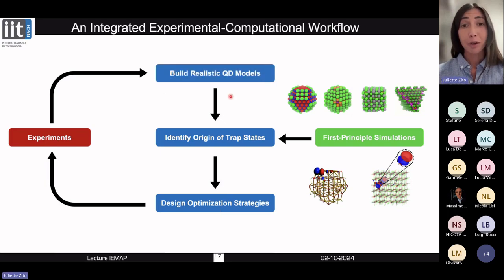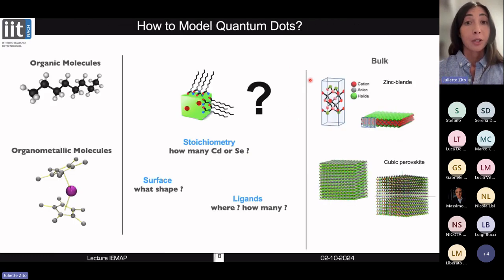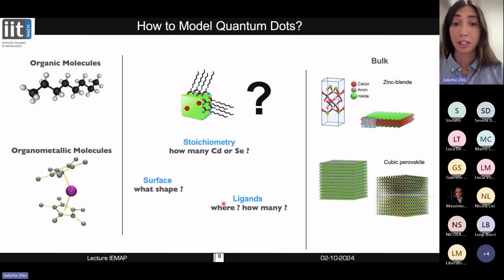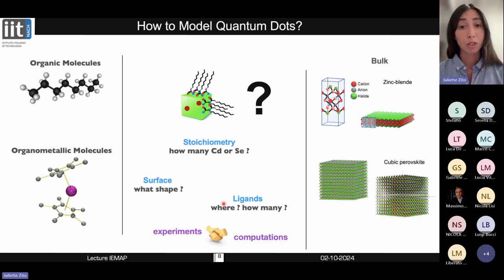So everything starts with building a realistic quantum dot model in order to understand and describe in atomistic detail the surface of your quantum dot. This is already a challenging step because, unlike organic molecules or bulk materials where you do have a fixed stoichiometry, so for example, in this molecule, you know that you have 8 carbon atoms and 16 hydrogen atoms, in the case of quantum dots, you have variable stoichiometries. Also, you have variable shapes and faceting, and you don't know where the ligands are, how many there are, etc. So building a realistic quantum dot model really requires a synergy between experiments and simulations.